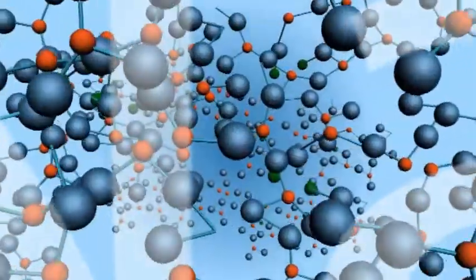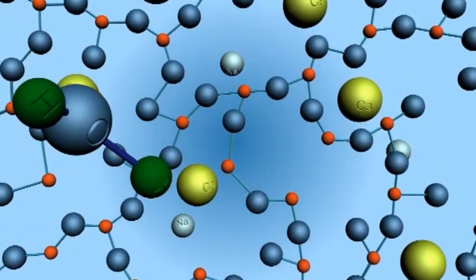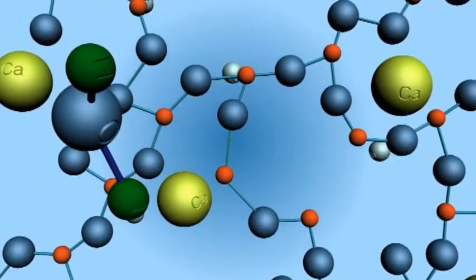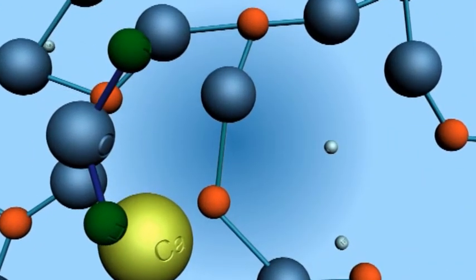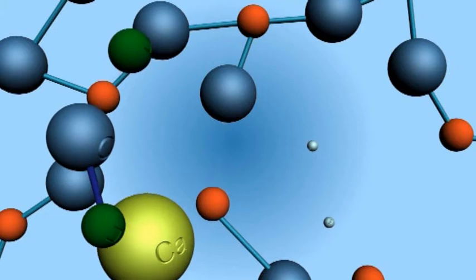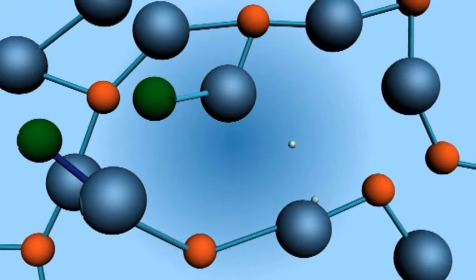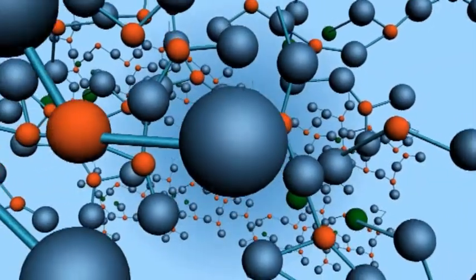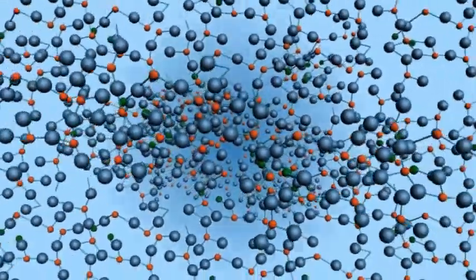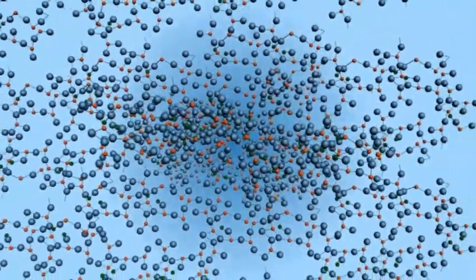With Bonalive bioactive glass, contact with body fluid and tissue causes leaching of ions starting with those most likely held within the matrix. Sodium leaches first, and then calcium ions also start to become loose. The leached ions are replaced with hydrogen and hydronium ions. In the resulting alkaline microenvironment, the bonds between silicon and oxygen atoms start to break at the surface of the glass.